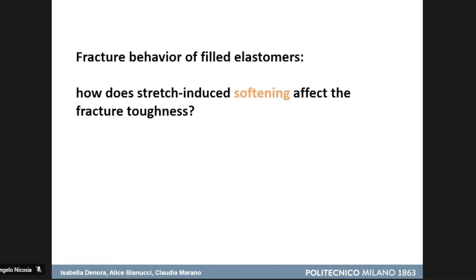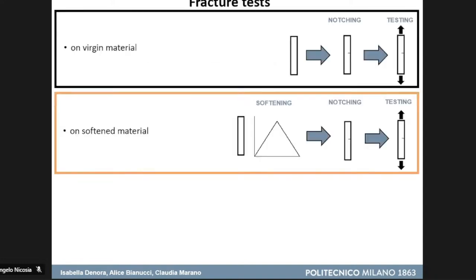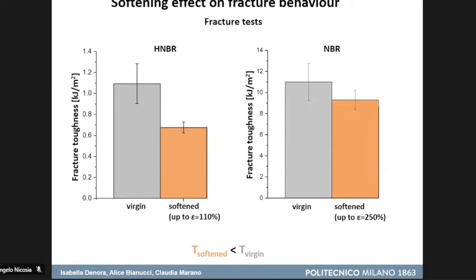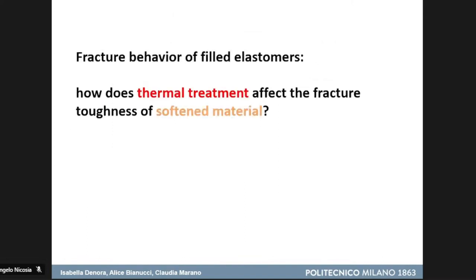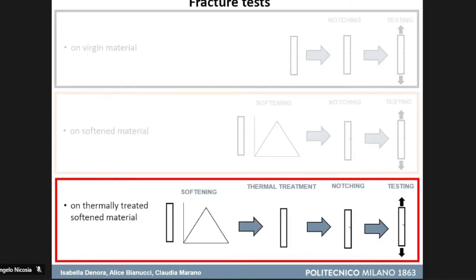We wanted to see the effect of softening on the fracture toughness of the material. So we have performed fracture tests both on the virgin material and on a material that has been previously softened. And here there are the results. So on both the two materials we obtained similar results. The fracture toughness of softened materials resulted to be lower than that of the virgin one. And moreover, we've also applied the thermal treatment on the softened material. So we have performed fracture tests on material that was previously softened, and then thermal treatment was applied before performing the fracture test.